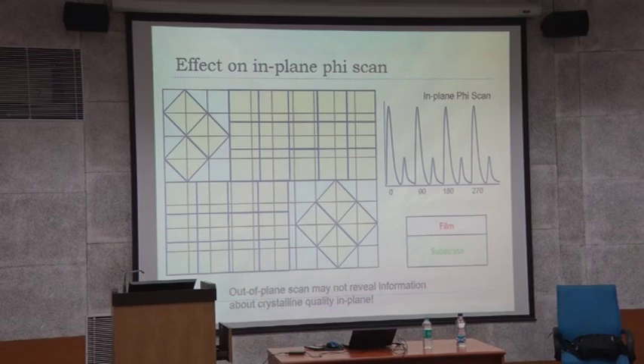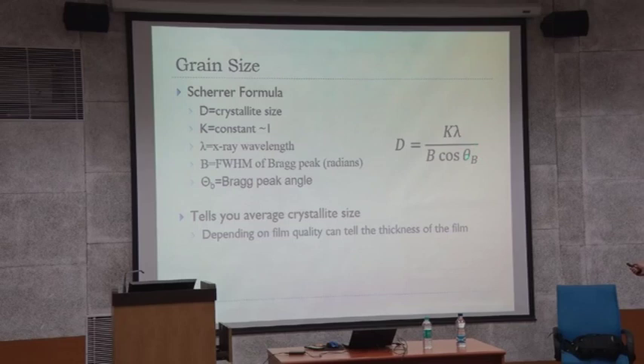So that's a way of mosaic spread measurement, or in-plane crystallography. There's also a grain size formula I'll share. You can do the measurement of grain size by this peak width — set up the regular Bragg condition of the peak, and put the width in terms of radians, not degrees. The radian value at the Bragg angle, specifically the cosine of the Bragg angle — here the factor B is the width of the peak — gives the grain size.